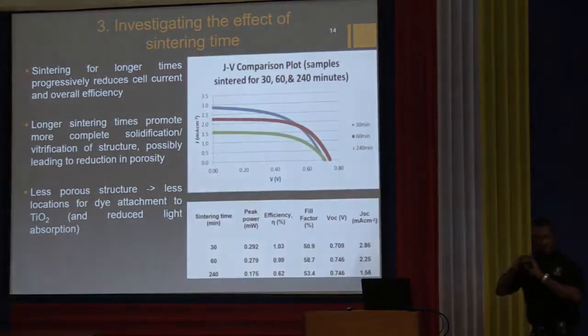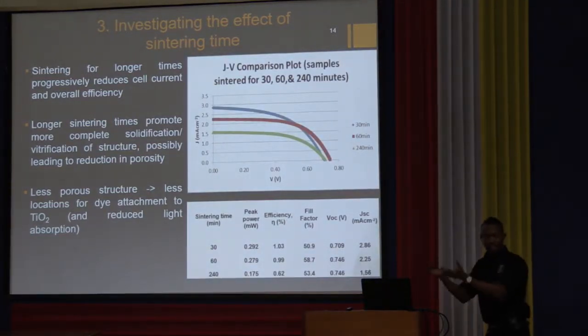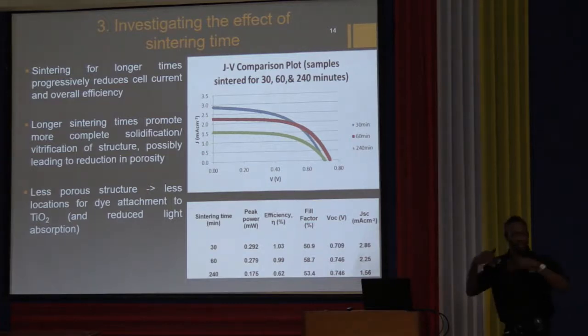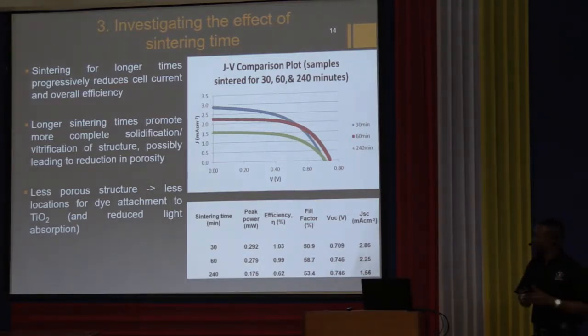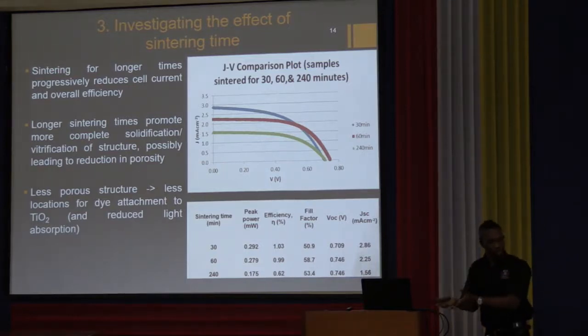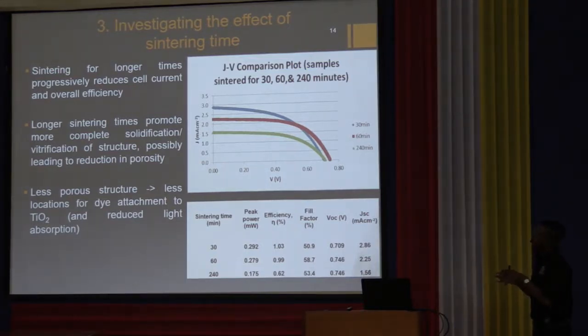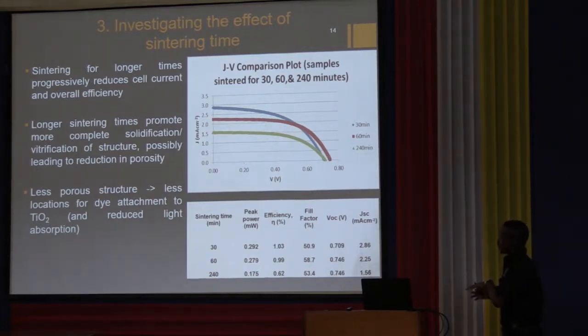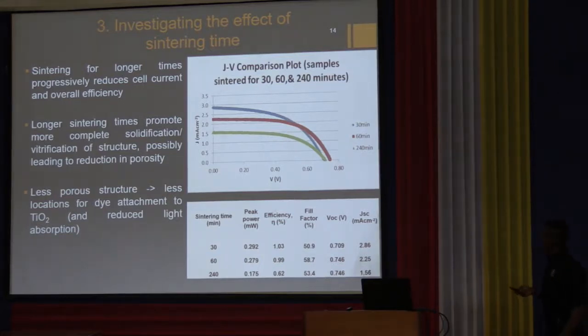So, remember, we took the best performing cell fabrication, the best performing cell paste with the best dopant at the best dopant level. We investigated that at the best temperature, and then now we took the combination of these two and investigated the sintering time. So we kept it at 400 degrees and measured how the efficiency changed at sintering times of 30 minutes, 60 minutes, and 240 minutes. And what we found is that the best performance was for the cell that was calcined or baked at 30 minutes. After that, the cell performance decreased.